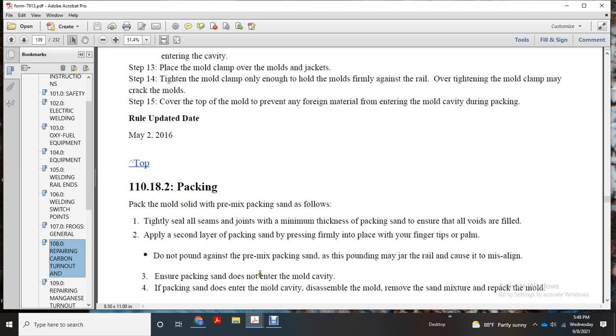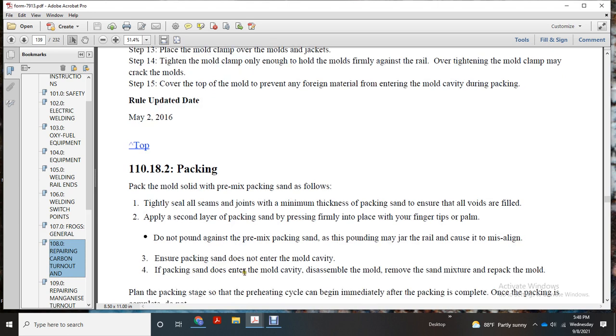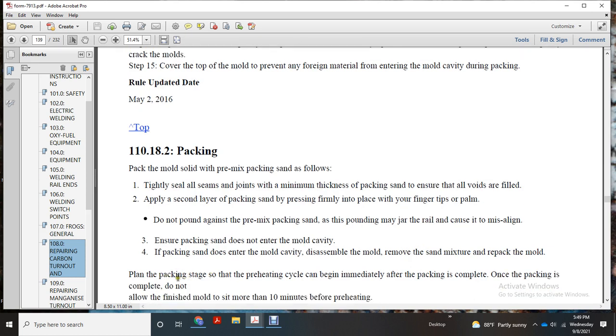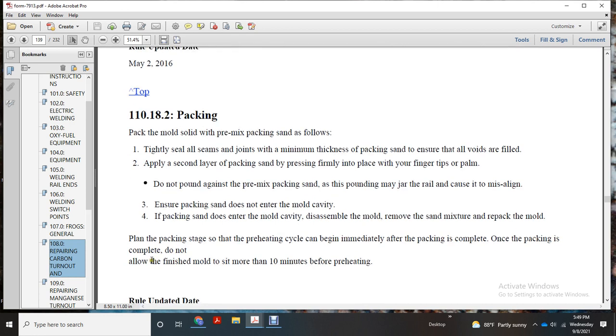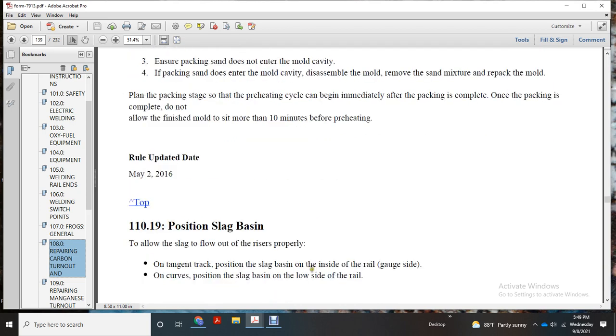Ensure the packing sand does not enter the mold cavity. If the packing sand does enter the mold cavity, disassemble the mold, remove the sand mixture, and repack the mold. Plan the packing stage so that the preheating cycle can begin immediately after the packing is complete. Once packing is complete, do not allow the finished mold to sit more than 10 minutes before preheating. Position slag basins to allow the slag to flow out of the risers properly.